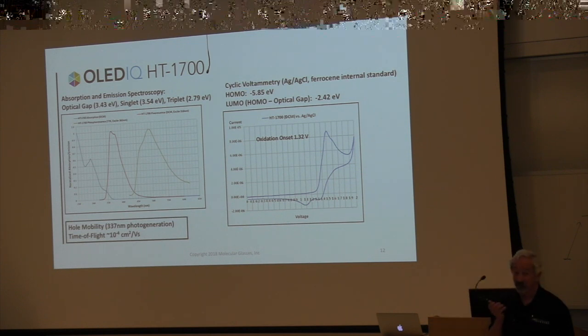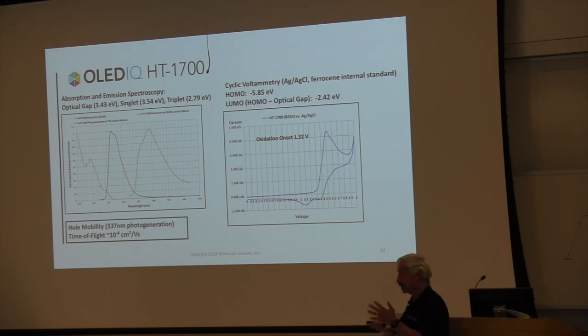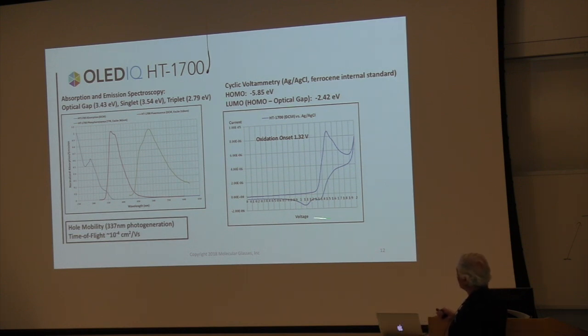So one of the things we have to do is characterize these, because if we're going to give samples or sell samples to companies, they're going to say, well, what is it? Again, this is difficult for a materials company because you need equipment to do that. And we slowly got equipment with the help of the funding that I mentioned. We got a fluorimeter, and absorption spectrometry, so now we can do absorption, fluorescence emission, and phosphorescence emission. So we can determine the energies of these. We got a setup to do cyclic voltammetry, so we can determine the oxidation and reduction potentials. And from this information, we can get the highest occupied molecular orbital and the lowest unoccupied molecular orbital.